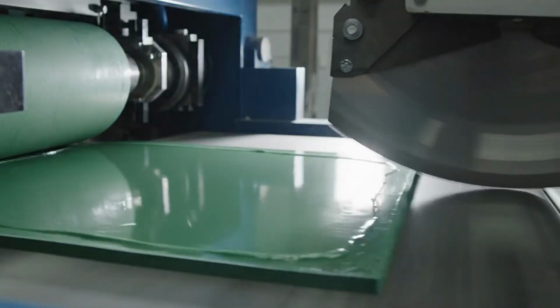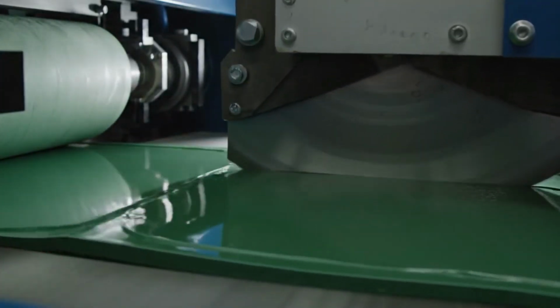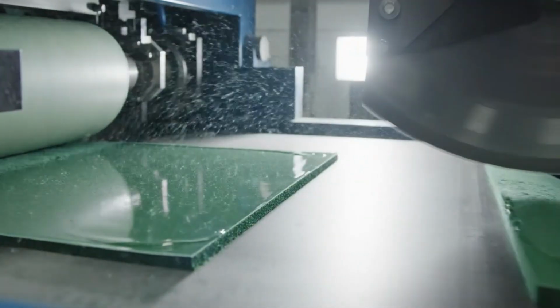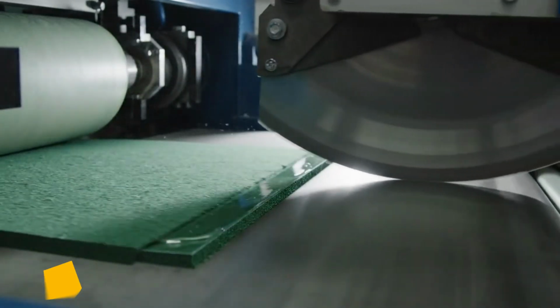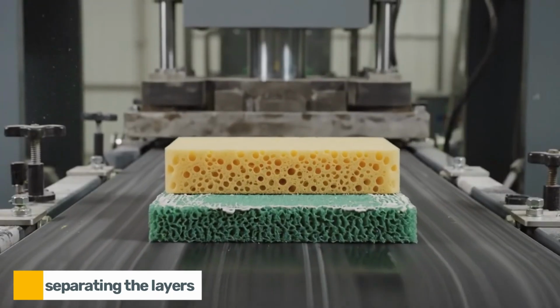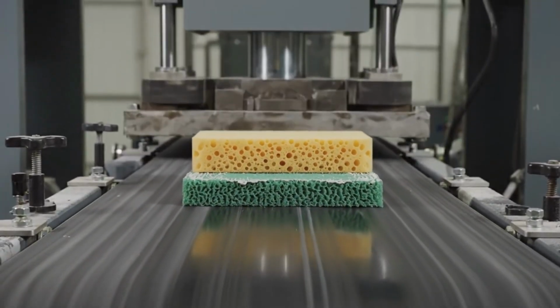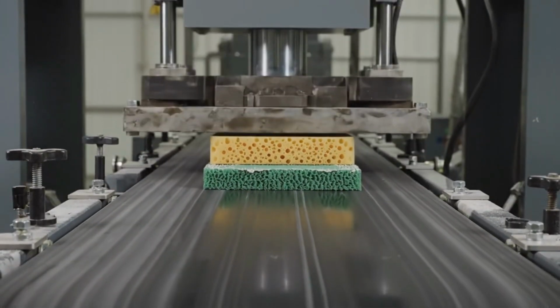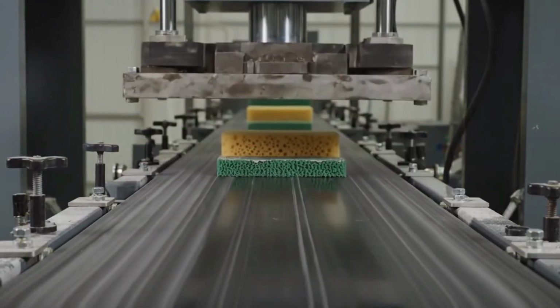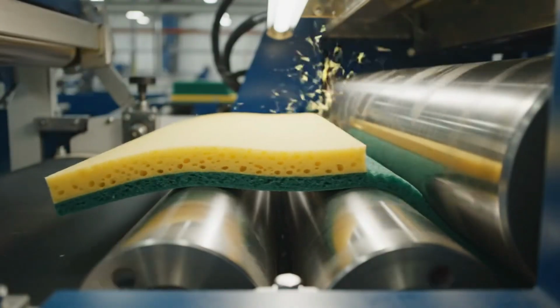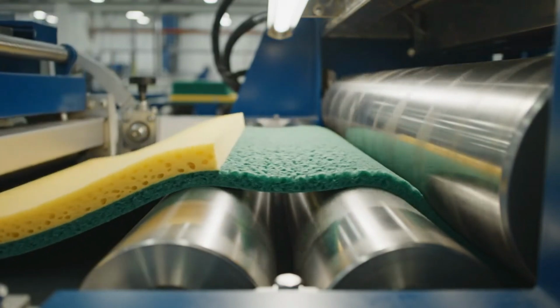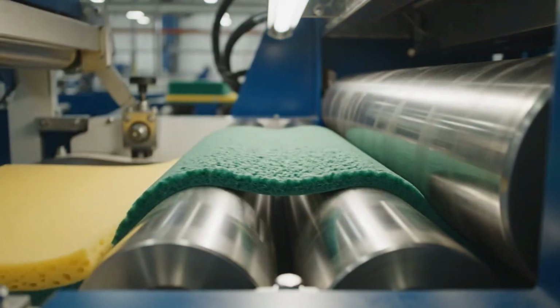The laminated sheets rest while the bond cures. Quality workers pull sample strips and perform peel tests, separating the layers by hand or with a small testing machine. If the scrub pad lifts too easily, the line is adjusted. Adhesive amount, pressure, temperature, and moisture all affect bond strength. The bonded sheets move into final cutting.